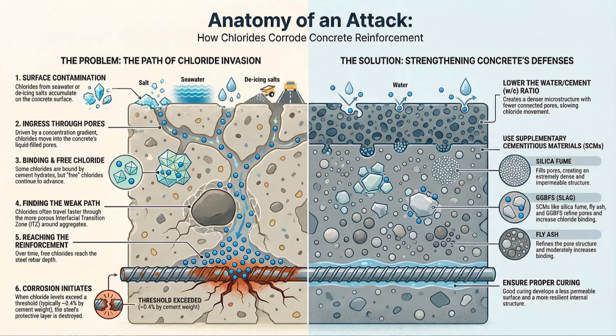Okay, so if you take a moderate baseline environment of, say, 20 degrees Celsius. Right, like we said, Northern Europe. Perfect example. And you compare it to a typical Gulf summer average of 40 degrees Celsius, the effective diffusion coefficient, the D of that concrete, typically increases by 50 to 100%. 100%. So the structure is already aging twice as fast just because of the air temperature. Twice as fast. And the real-world applications, the field data, it shows this acceleration is just relentless.